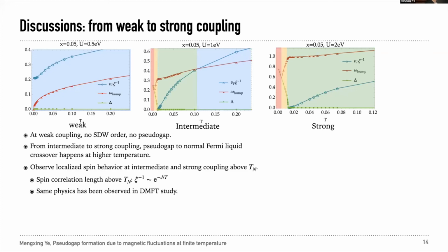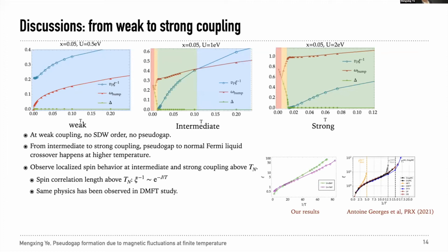And we can also look carefully at how the spin correlation length behaves as a function of temperature. We find that this spin correlation length scales exponentially with inverse temperature, as you can see here. For comparison, I also show the result from the DMFT studies. And this straight curve essentially means it is exponential behavior in the log plot.